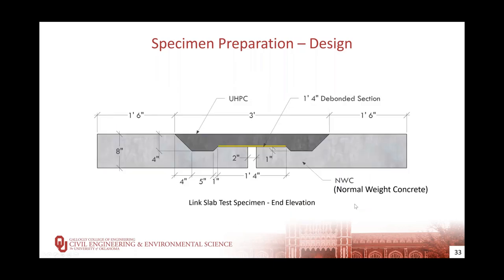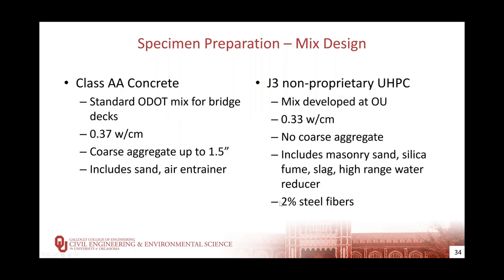Here's a more detailed look at the profile of the specimen. Note the debonded section. This will allow the connection to behave more like a simple span end than a continuous connection. The New York State DOT detail calls for a compressed synthetic sheet gasket for the bond breaker. We were actually able to purchase and install the same bond breaker used by the New York State DOT. As mentioned, we use the class AA concrete and J3 non-proprietary UHPC mixes for the connections. The class AA mix has a water cement ratio of 0.37 and included coarse aggregate up to 1.5 inches in size.